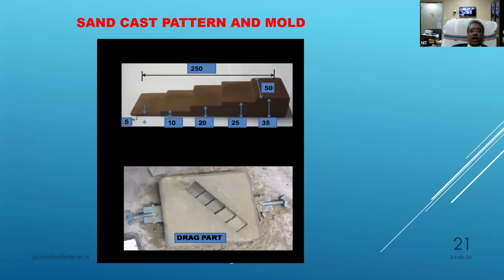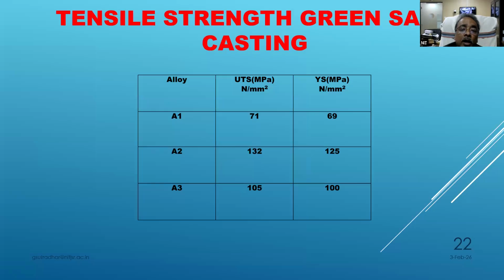So this is the pattern you can understand, that is a wooden pattern, and that is a drag part of the pattern. Then we have taken samples from the different alloys. That is A1 alloy, it is giving UTS, then yield stress. See that the A2 alloy is giving maximum UTS and maximum yield stress.